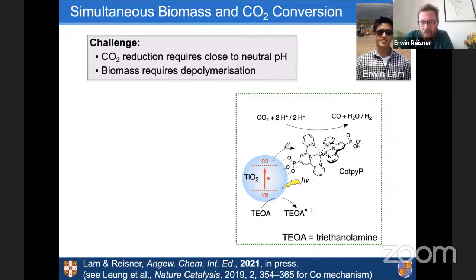And the one we identified, in fact, from previous work by Chen Liang here, is this cobalt bisterpyridine catalyst. They have been known for quite a long time, but the surprising finding we had is if you phosphonate them and you put them on a surface, the mechanism changes. And this change in mechanism means that you only need to go to the cobalt 1 rather than the cobalt 0 state. So you can access cobalt catalysis with cobalt 1, which is sufficient with the driving force of titania. And in fact, this is the first system on titania that shows CO2 reduction with a molecular co-catalyst.